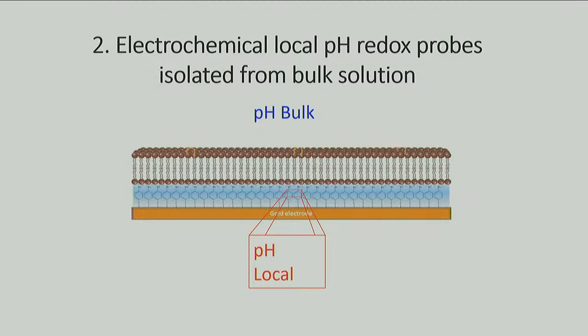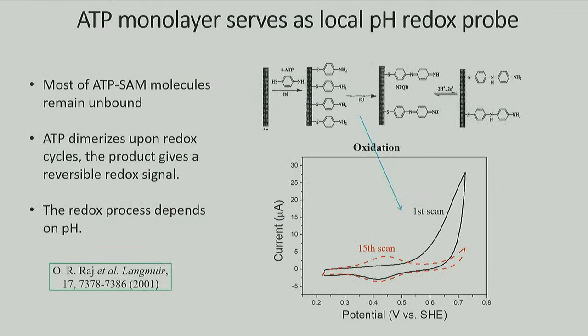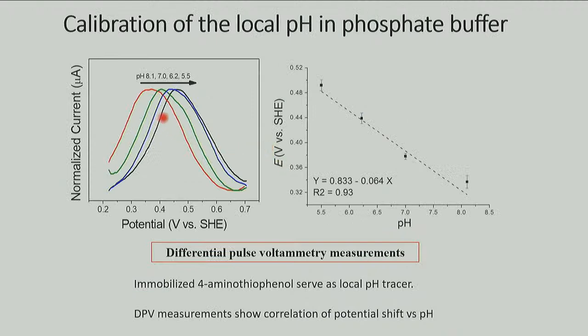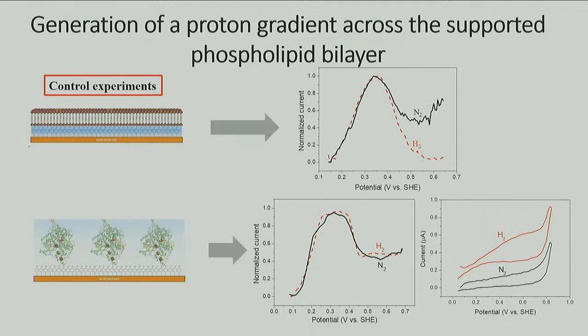It's very easy to measure the bulk pH with a pH meter, but how do we measure the local pH under a membrane? So we developed a monolayer of these compounds that can dimerize after application of a potential sweep. This is going to be a redox probe. It can oxidize and reduce this amino to imino, and depending on the pH, this is going to shift a little bit, like this. We can see that when we put this monolayer, this is going to move with the pH towards here. This is the potential sweep, and it is a linear relationship. We can measure the local pH under the membrane.